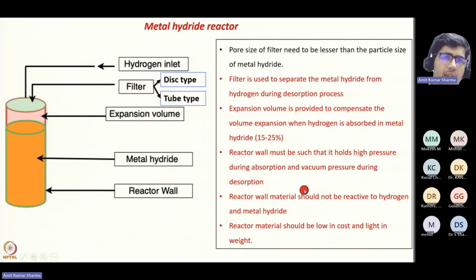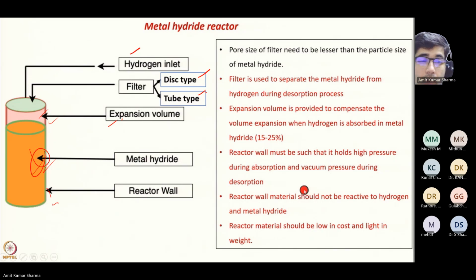So this is a diagram of a metal hydride reactor. Here we have the hydrogen inlet, then the filter, disc type or tube type, then we have the expansion volume here, then the metal hydride reactor wall. The pore size of the filter needs to be smaller than the particle size of the metal hydride. The filter is used to separate the metal hydride from the hydrogen during the desorption process. Expansion volume is provided to compensate for the volume expansion when hydrogen is absorbed in metal hydride. The reactor wall must hold high pressure during absorption and vacuum pressure during desorption. The reactor wall material should not be reactive to hydrogen and metal hydride, and should be low in cost and light in weight.